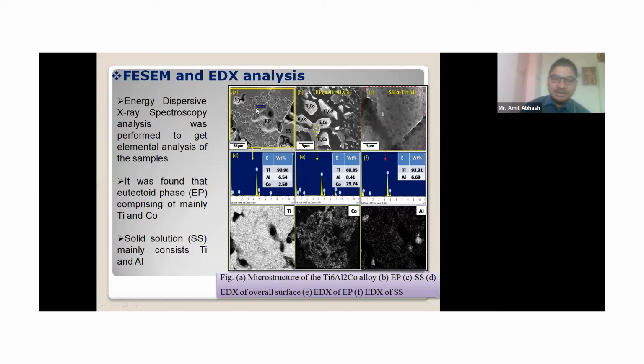So we did the overall mapping, overall EDX analysis, to ensure the amount of matrix material and alloying element. We can see here the overall surface EDX analysis. The titanium weight percent is 90.96, almost 91. Aluminium is 6.54 and cobalt is 2.50, which is almost equal to the Ti6 aluminum 2 cobalt alloy. The 6 aluminum is also optimized data, and I have published this in Material Science Engineering C.